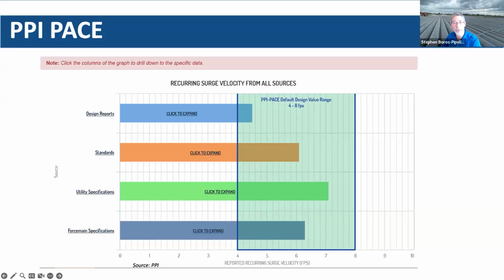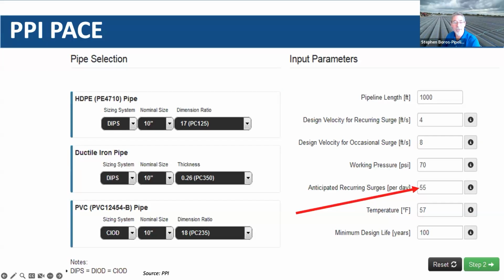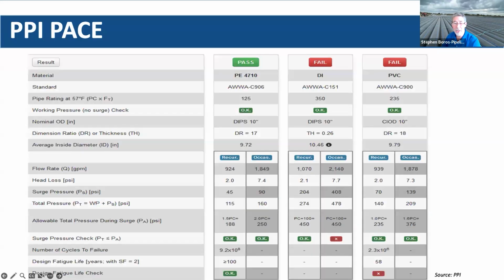at peak demand situations. On surges, like I said, if you look at the design manuals for polyethylene, PVC, ductile iron, specifications from a lot of major utilities, on a force main design, it's 55 surges per day. That's a lot to take into account. And PPI PACE helps you do that, because ultimately that's going to be how these materials fail, is by cyclic fatigue, if the material is susceptible to that. So once you put in all your parameters, then you get the actual design.